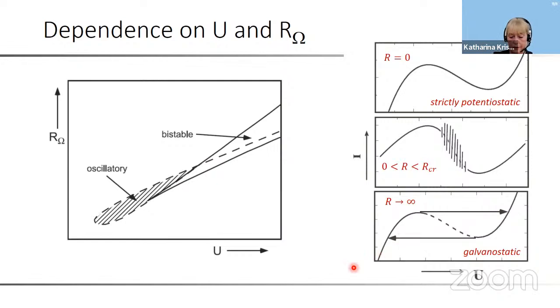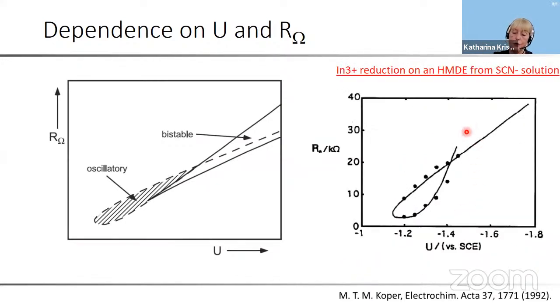But before, I should show you some experimental results. In fact, here again, we have the indium ion reduction on a mercury electrode. The form of the region in the parameter plane spanned by the resistance and U looks very similar to what is predicted from the equations. So, and this is general to all N-NDR systems, independent of the cause of the NDR.